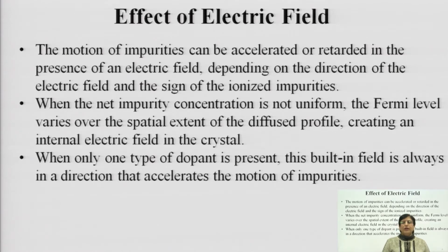So, effect of electric field. As you know, as we studied in the previous lecture, the diffusion process is basically the movement of dopant species within the bulk material. And this movement is because of two typical things: one is known as vacancy and the second is substitutional defects, where these species substitute the host atoms, dislodge them, occupy their places, and thereby move within the bulk.